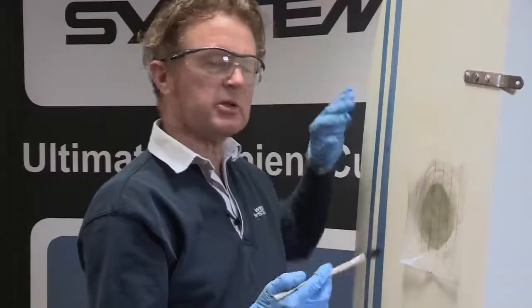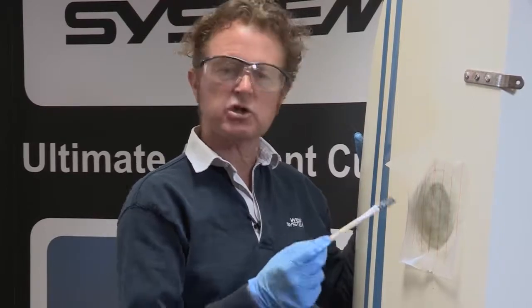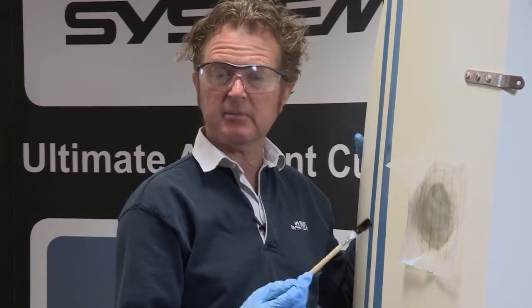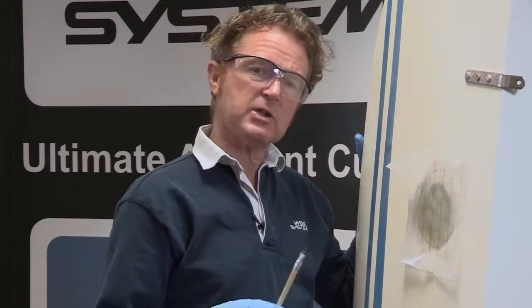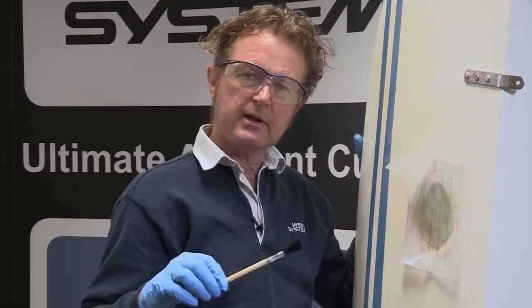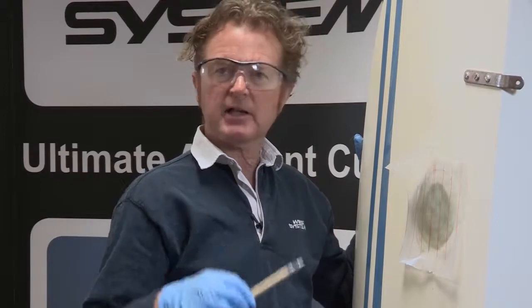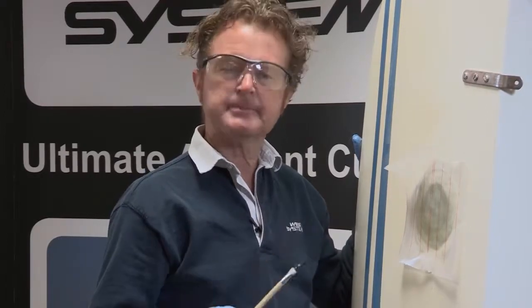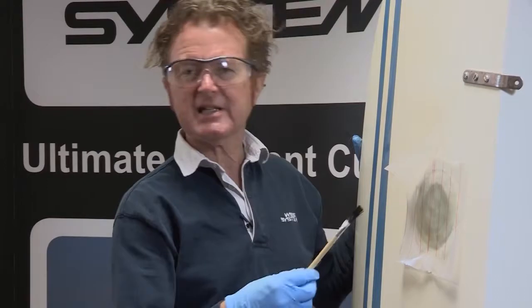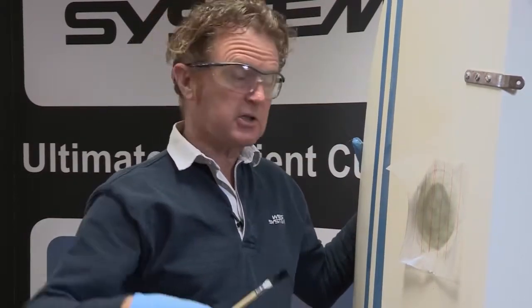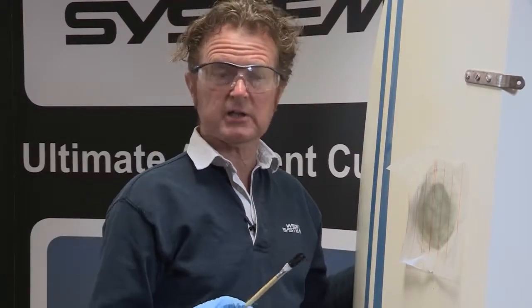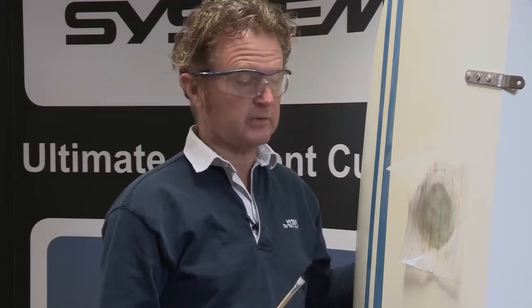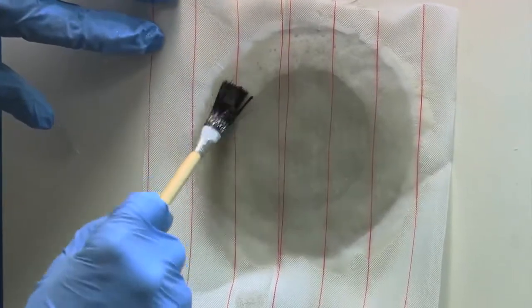Now, this looks fantastic. I'm doing this work in a lovely, warm environment, but there's no reason why you shouldn't be able to effect this kind of repair in the dinghy park, given good conditions. Once the temperature dips below double figures, then the epoxy starts to become thicker, starts to become more unwieldy. But it's easy to create a small tent around the work area with a small blower heater to introduce some good working conditions to your work. It will improve the quality of what you're doing. It will improve the success of what you're doing.